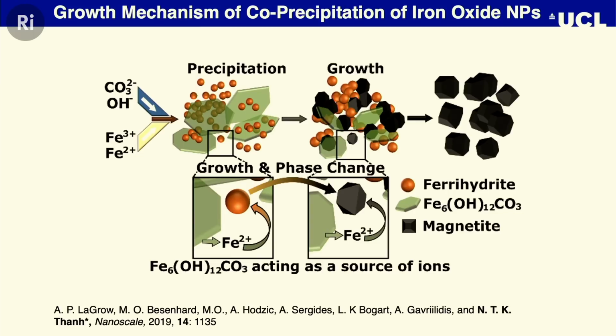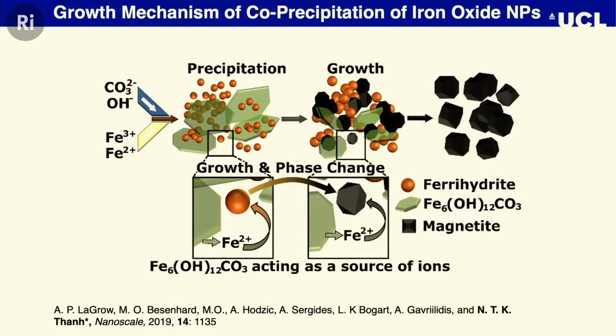Why? Because for more than 40 years, in the field, you can see that people report different values of saturation magnetization. There is no consistency, because they form intermediates. So when you have two flows and you get the reaction, you can see that from precipitation, you get orange, the ferrihydrite, and you get this green plate, which is a carbonate. But then they go into the next phase where some ions from this green plate leach out and interact with the orange ferrihydrite, and then some more ions from the green plate react with the ferrihydrite, forming this magnetite. That's what we want, that high magnetic moment phase.